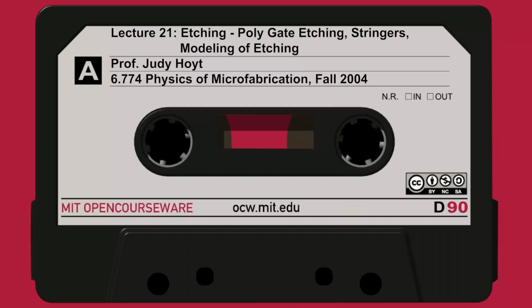People use the ordinary process to make a polysilicon gate. So you put down poly, you etch it, you make your sidewall spacers. So that's just like what we learned about in this course. And here is a very short channel MOSFET. Here's a very long channel MOSFET. Now, at the end of defining your MOSFETs, you put down this gray material and you put it everywhere, very thick. So you put down a dielectric and then you CMP it down. So you have dielectric that's been CMP'd and flattened. The polishing stops just around this height.